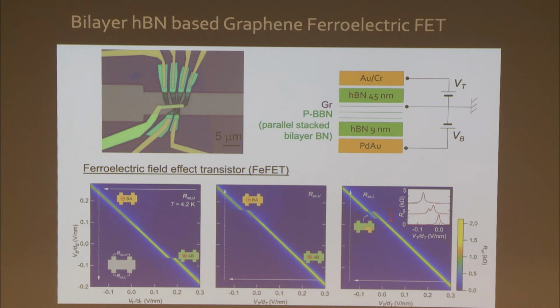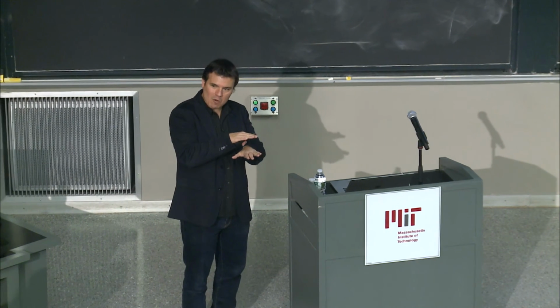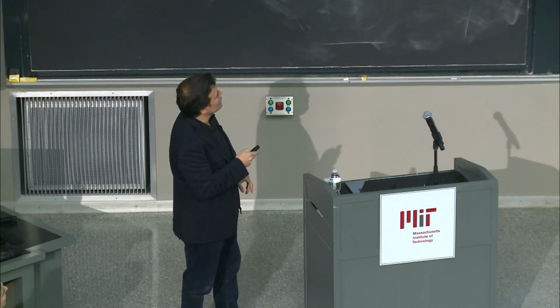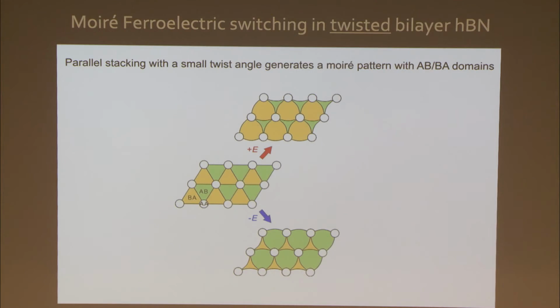Okay? Now, this is for parallel stacking. What happens if we introduce a small twist angle? Okay? If we introduce a small twist angle, then we actually have a moire ferroelectric, or better, antiferroelectric system. Okay? Because now you have those AB/BA domains similar to twisted bilayer graphene, but now these are domains of opposite electric field, alternating up and down. Okay? And with an electric field, we can increase one type of domain or the other if we reverse the electric field.